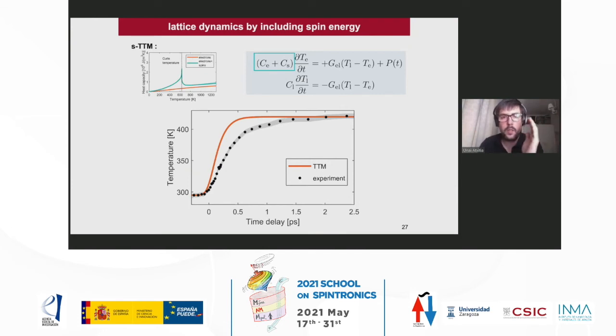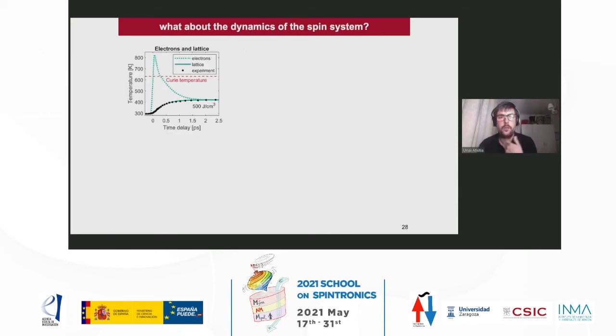So the effect is that the dynamics of the lattice temperature reduces, and once we introduced the specific heat of the spins into the model, we obtained a perfect agreement - not only for one fluence, but for all fluences that we investigated experimentally.